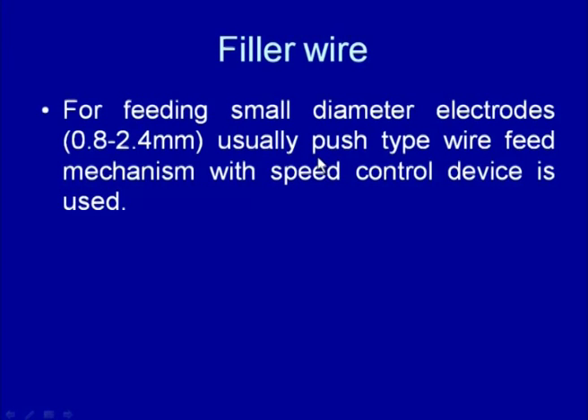The filler materials may be of different sizes, different diameters and lengths, depending upon the base material which is to be used and its thickness. For feeding small diameter electrodes like 0.8 to 2.4 mm size, normally a push type wire feed system is used if mechanized feeding of the filler wire is to be done. But in most practical situations, we can feed the filler wire manually also.